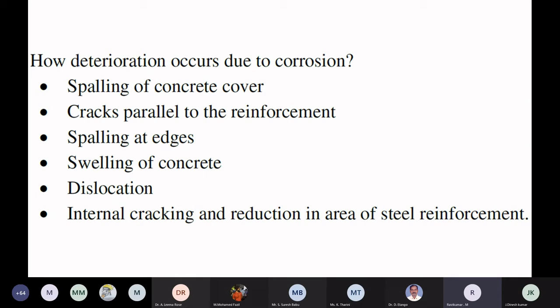So when you look closely at the exposed reinforcement, the rebar may be corroded. Because, friends, when corrosion starts in the reinforcement, the volume increases 5 times. When the volume of the steel increases due to corrosion, tension develops along the length. Because concrete is weak in tension, a crack develops along the length of the bar. And since the volume increases due to corrosion, it pushes the outer concrete, that is the cover concrete. That's why you are seeing the spalling.